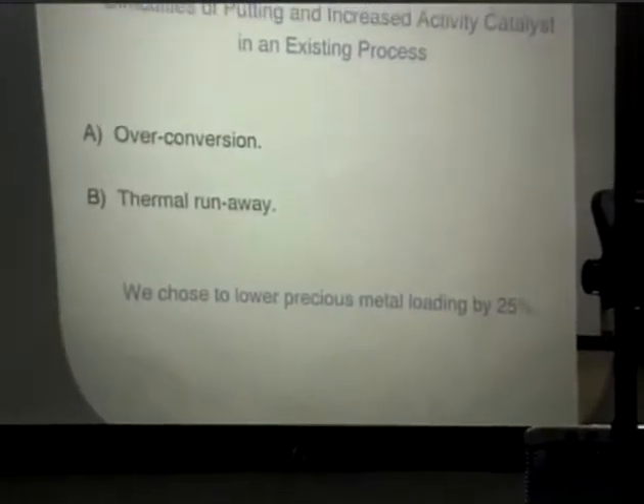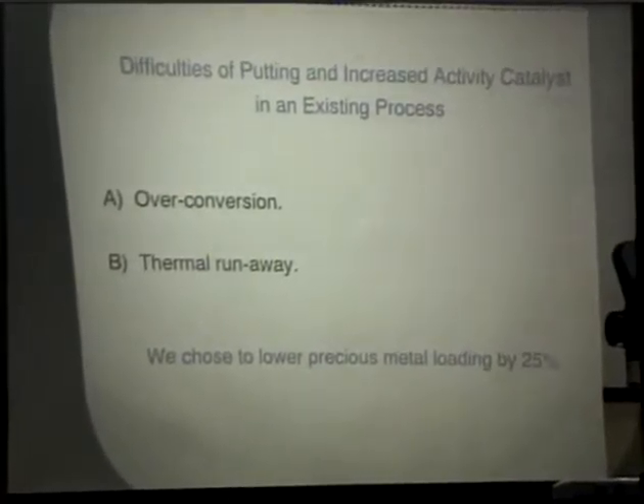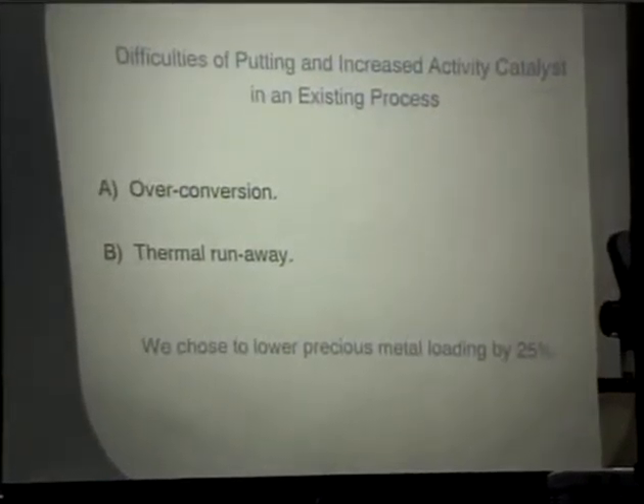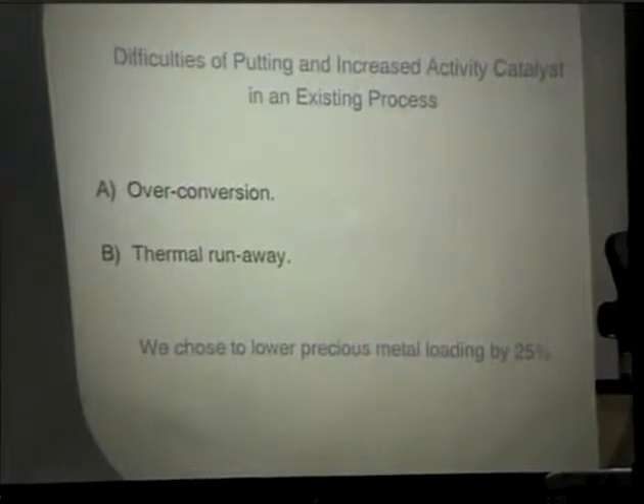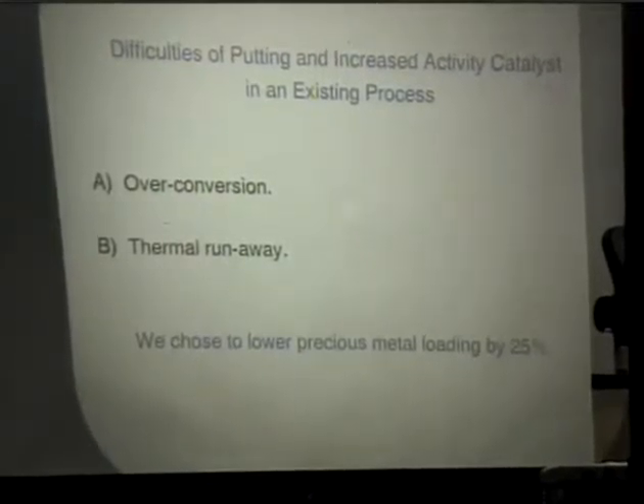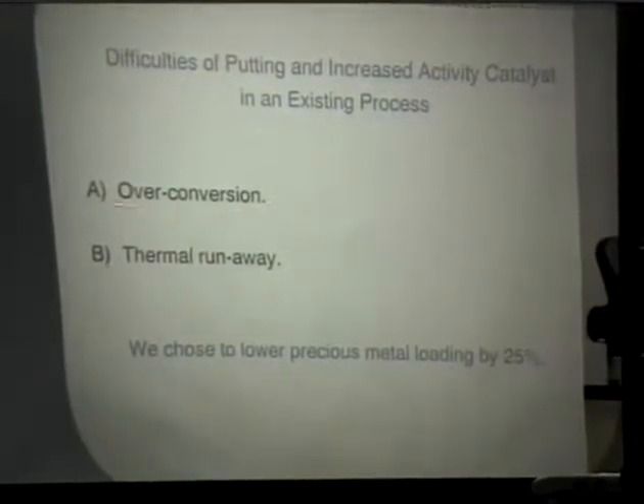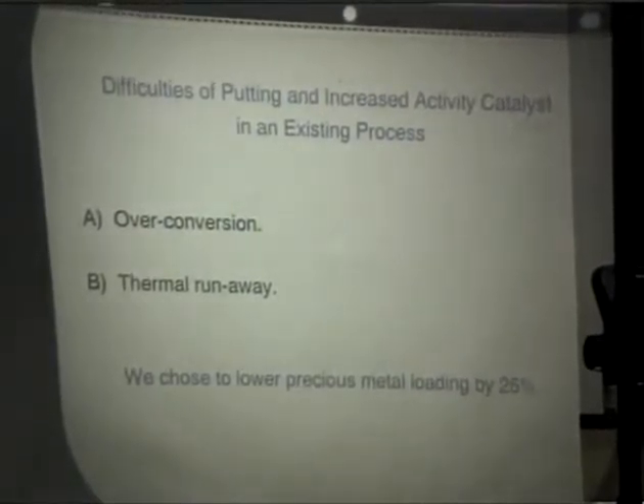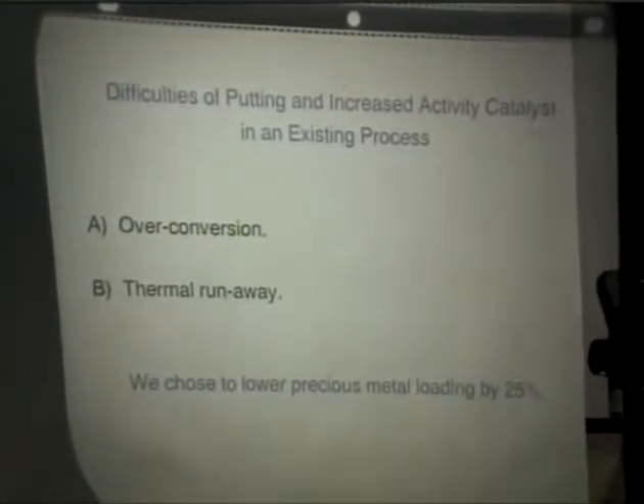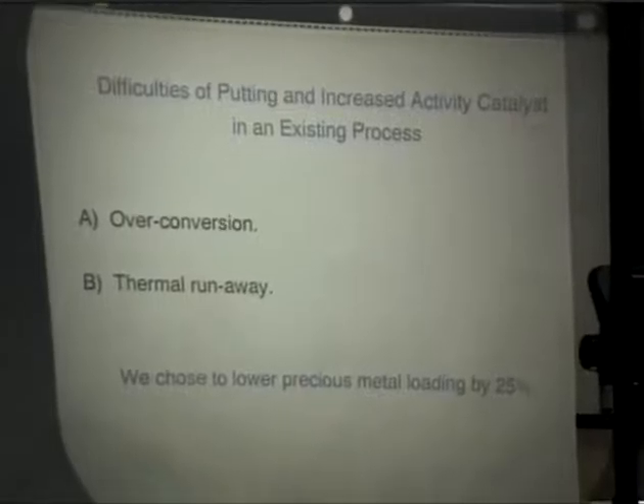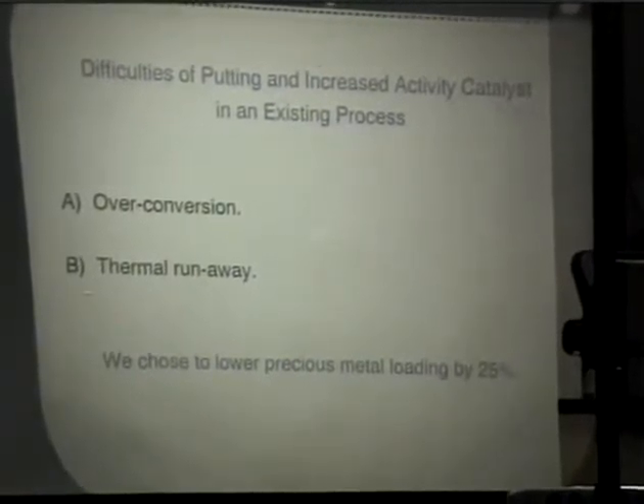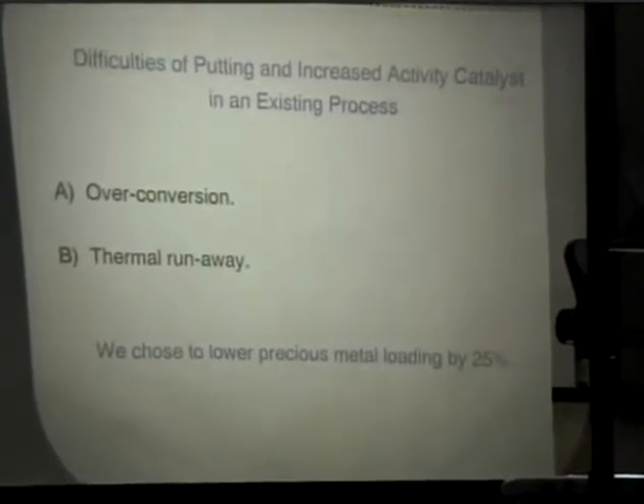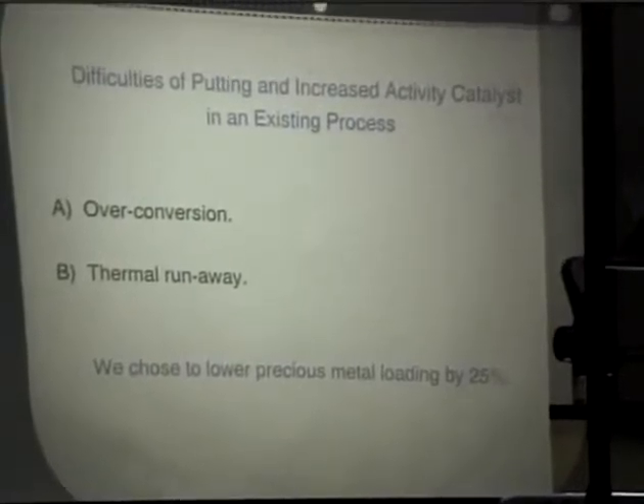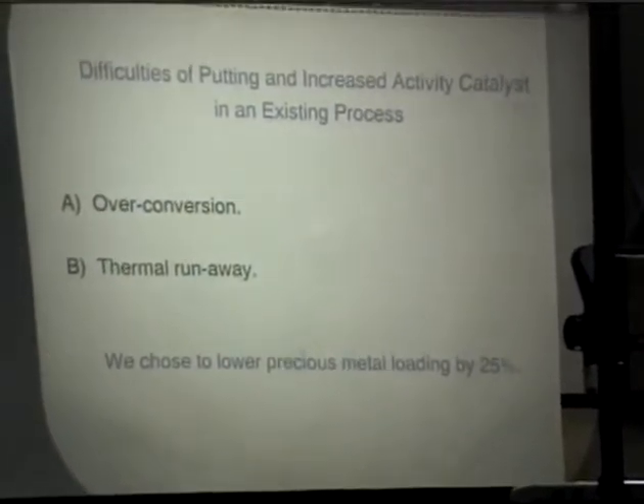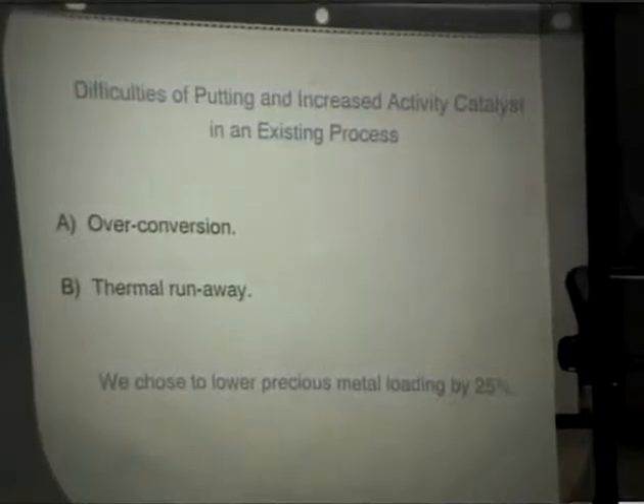We have an existing process, and so you have a catalyst that's more selective. It's very easy to put into an existing process, but a catalyst that's more active can be very problematic in an existing process. The first thing to think about is overconversion. And again, in an oxidation, the problem of overconversion is a loss of selectivity. You make a lot of CO2. But secondly, it's an exothermic reaction. And so when you're making all that CO2, how are you removing the heat? And there's a good potential for thermal runaway.